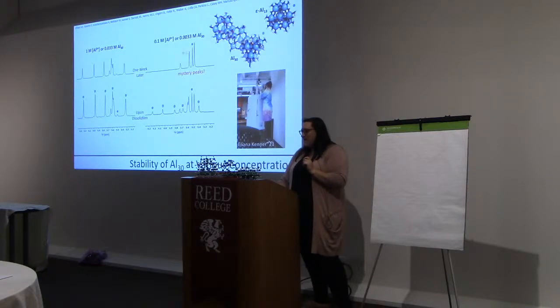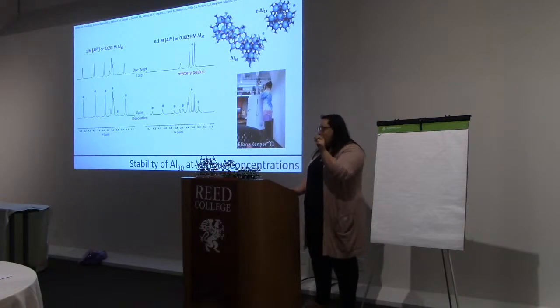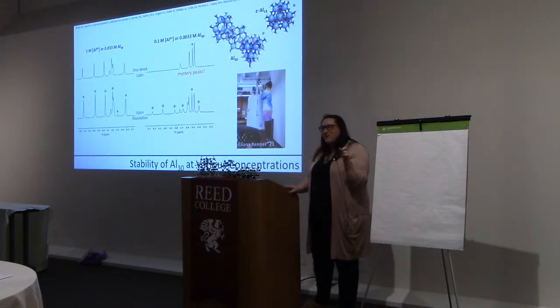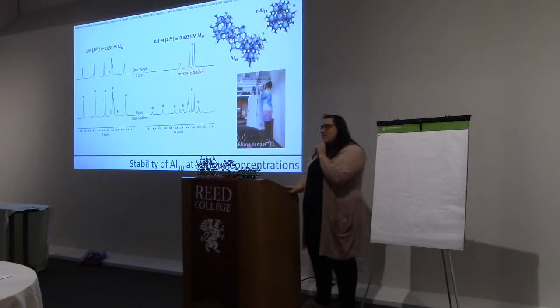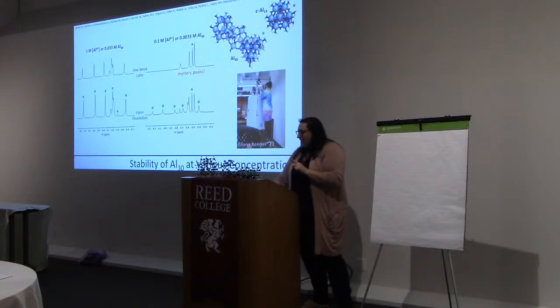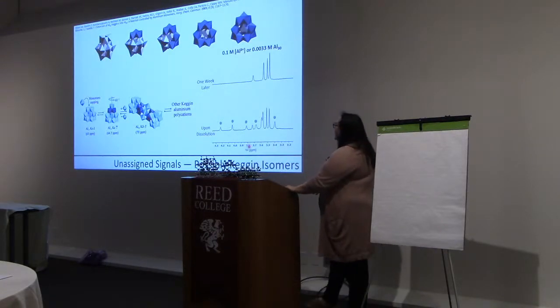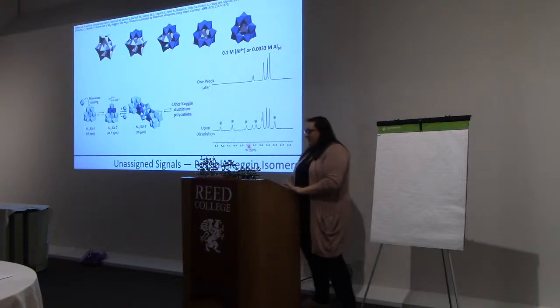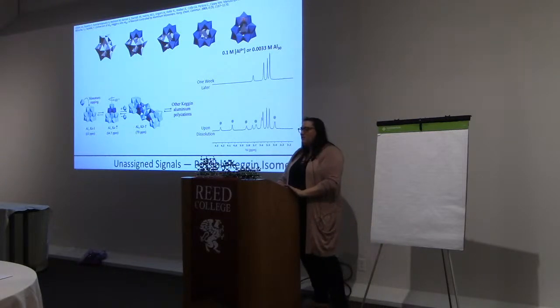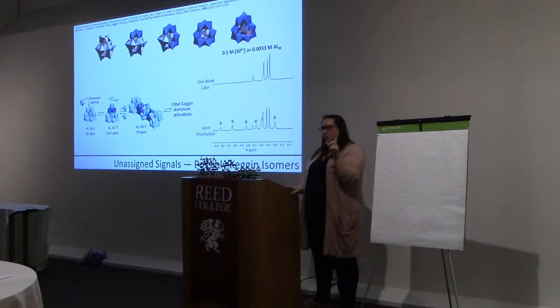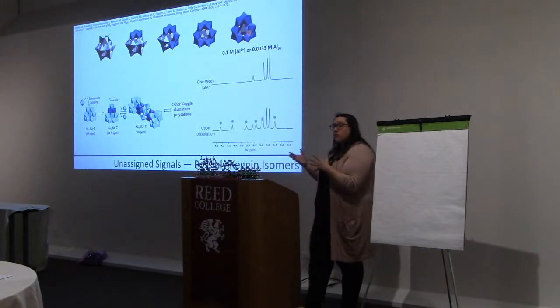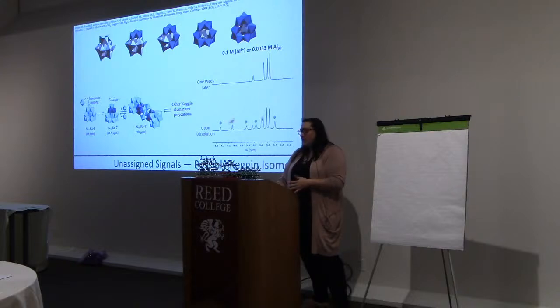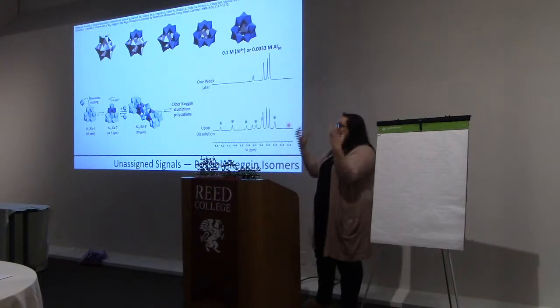We looked at that again at 0.1 molar. After a week, all the 30 was gone. And all that's left is our mystery peaks that were the impurity in that previous sample. And so now we know how to make a higher concentration of our mystery signals. My thought is that these signals might be some of our isomers. As you break the symmetry and rotate one of these, you're going to go from one signal, one type of hydroxide bridge, to a few more. And so this could be our delta, that as the 30 is falling apart, we have those delta isomers in solution, maybe even a gamma.